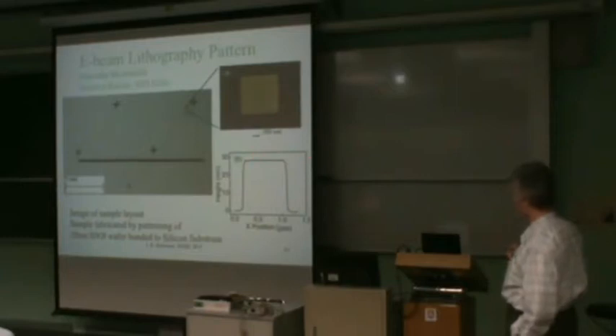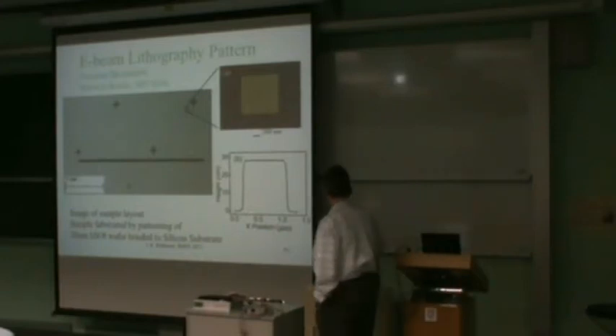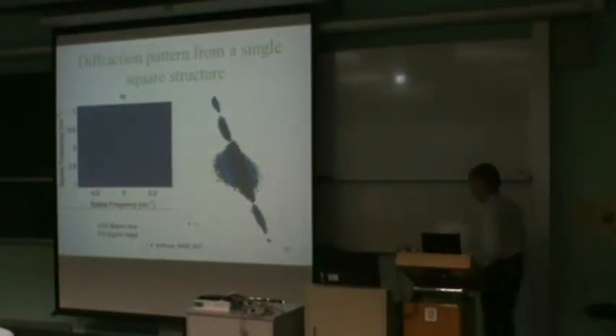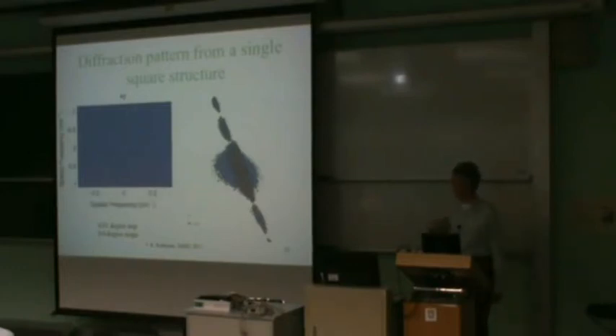The cross-section is relatively flat on top at the level of SSOI. So we then took these and looked at this square structure with X-rays, and you can see, if I can play it, we get a sequence as we go through the rocking curve of the distorted Bragg peak. This is the strained silicon Bragg peak, which is separate from the Bragg peak of the substrate.